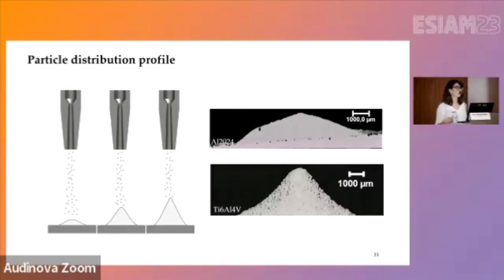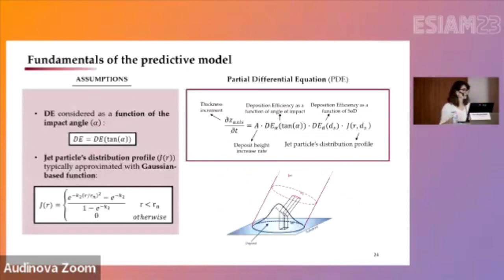So this is causing the problem for the shape control, because we cannot simply superimpose these triangles onto each other because of the dynamics of the process and the flow of the particles. And then that becomes a challenge in order to reach a target geometry. What we have done in this area is that we started from a model that was developed by Professor Klinkov a long time ago, considering the physics of the process and the distribution of the particles in the flow, and upgraded this model by adding additional features to give it much more flexibility in terms of the shape of the substrate, the trajectory of the nozzle, and the different parameters that would affect the shape prediction.